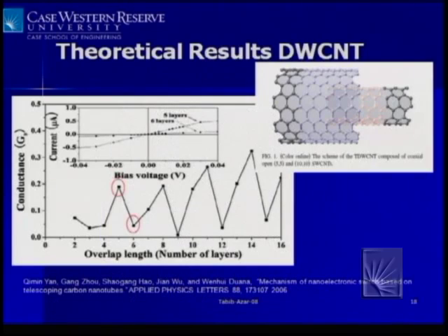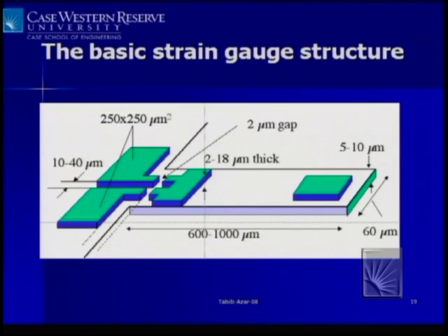There's another theoretical work that was done by a Chinese group, a very careful study, that showed that the conductance goes up and down as these different layers are telescoping against each other. So this was intriguing, but if you want to make a device with an AFM tip in there, I don't know about you guys, but that worries me, because then you have to spend $150K on an atomic force microscope to make a strain gauge that you're going to sell for a couple of cents, right? So it was interesting to use our self-assembled, self-welded technique to come up with devices that we can readily make, and they are scalable and reproducible.